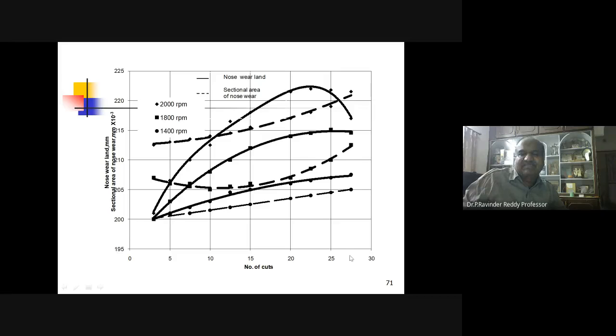And you can observe that against the number of cuts, when you increase the number of cuts, the nose wear is increasing. But after a certain level, you can observe that it is again decreasing. Whereas the sectional area of nose wear is increasing. These dotted lines are sectional areas. So there is a constant slope, right? This is linear. This is a small variation between these two at different speeds.